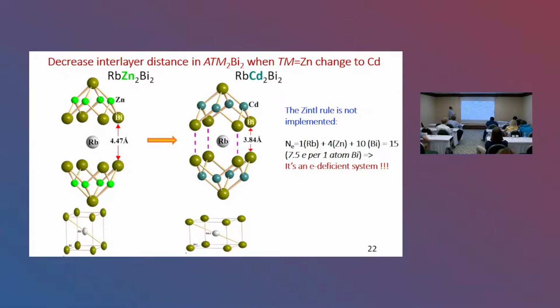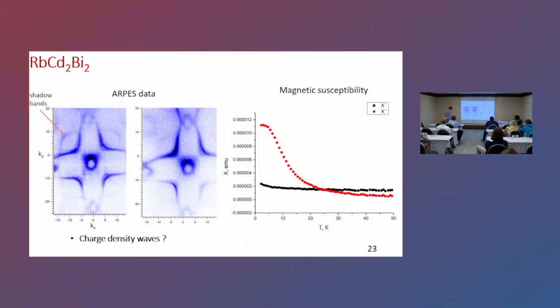If we use the effective ionic radius of bismuth 3 minus, about 2 angstrom, we conclude that there exists some interaction between the bismuth atoms in this case. I think this is very important because the preliminary results of ARPES measurements show very interesting shadow bands like in cuprates, and the band structure calculation gives the same result, a picture very close to that of classical cuprate superconductors. And in the magnetic susceptibility, we can see some interesting change at low temperature.